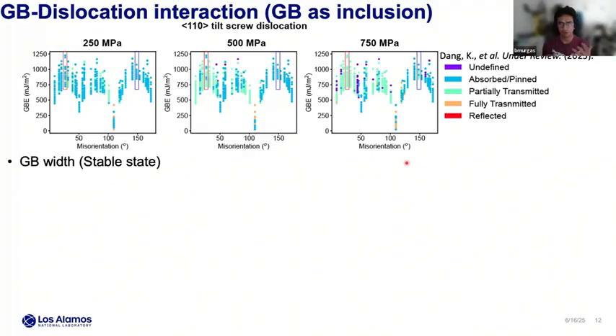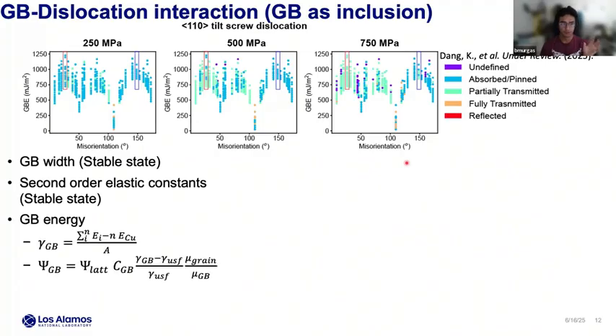So now for the PFDD, we have the width, we have the elastic constants, and what is missing, for the metastable states, is that the main change is the grain boundary energy. So what we proposed was to change the lattice energy based on this grain boundary energy that you can see here. So we have a different lattice energy of the grain boundary that is proportional to the bulk energy, this term here, but multiplied by a constant that depends on the grain boundary energy.